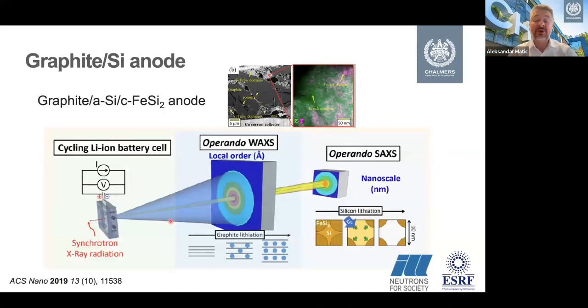So the materials become more and more complex, and to reach higher capacity, another trend is to mix graphite with some silicon. Silicon has a larger storage capacity than graphite, but the problem is a huge volume expansion. So one tries to make really nice composites that can withstand this volume expansion, but still store a lot of lithium. So in this experiment, colleagues from CEA in Grenoble did experiments with neutrons and X-rays at ILL and ESRF.